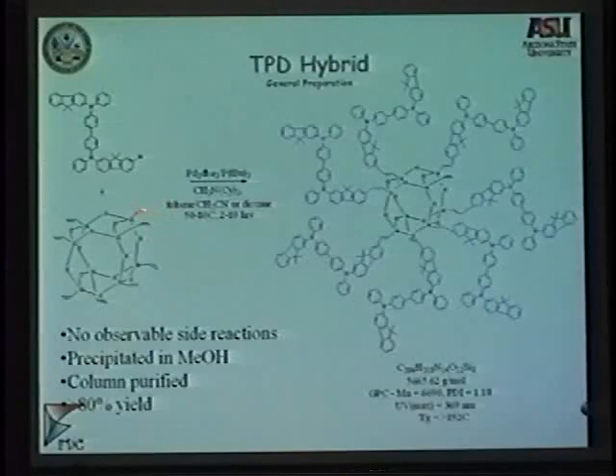We functionalize this with these light emitting and also hole conducting materials, and as you could see, you could connect them covalently, so there is no phase separation when you mix these things together. You can connect them covalently at all the 8 sides of the cube. And you can control the concentration of these. You can have only 1, you can have 2, you can have 3, and you can have up to 16, even though there is only 8 sides of the cube. It turned out you can put 2 of them on this bond right here for some reason that we don't